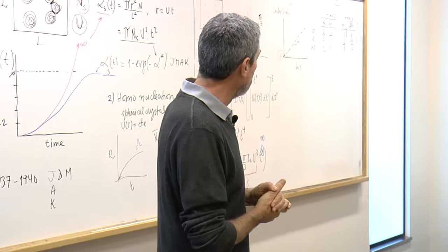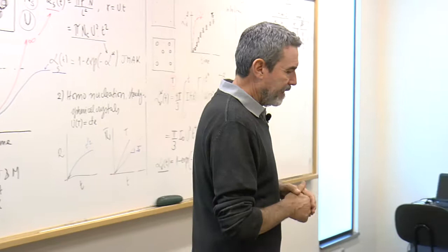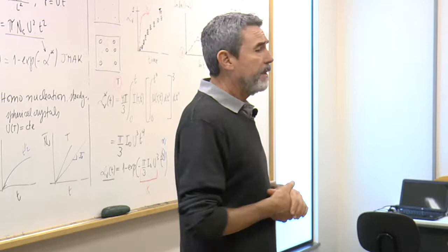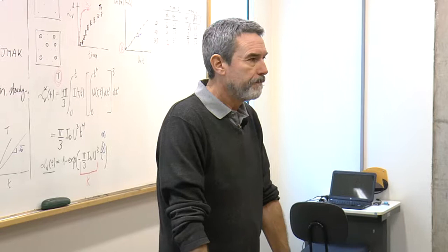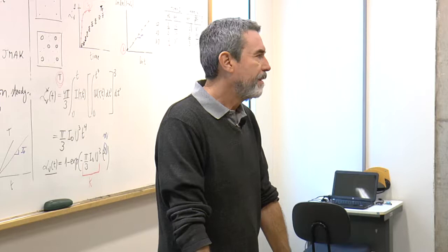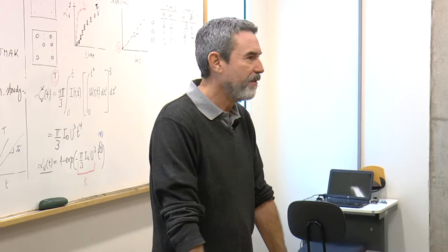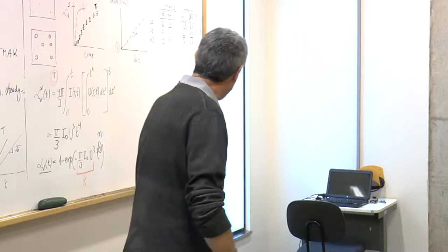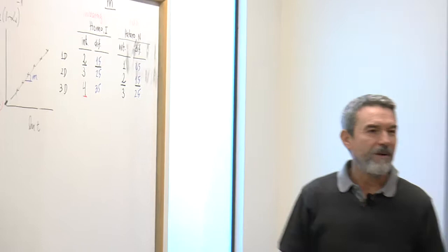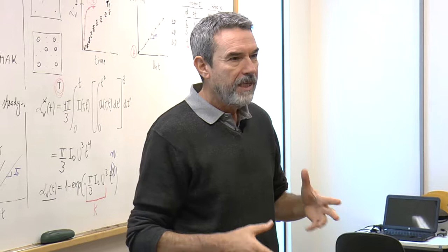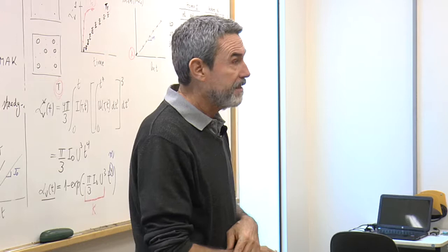Like, I was attending a conference called Material Science and Technology 3 weeks ago in the USA, and one guy was giving a talk on calculating these Avrami coefficients for some particular glass using DSC. Well, his M values varied like crazy, but for some systems, the M was 7.5. I told him something is wrong with your calculations. It cannot be larger than 4. It was 7.5. I don't know what's wrong. It was a short paper, 15 minutes. You cannot visualize what was wrong, but from the end result, it was easy to predict that something was wrong there. 7.5. You'll never find this.